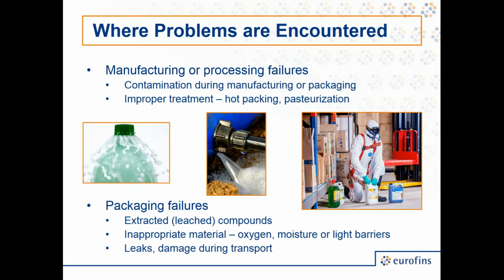So as we dig a little deeper into the contributing factors for where these problems come from, we like to go upstream because we all want to get to, obviously, root cause analysis and corrective action. So manufacturing and processing failures oftentimes are going to be during the manufacturing or within the packaging steps. And oftentimes it can be from improper treatment, like inadequate hot packing, pasteurization, maybe some type of contaminant that's present from a maintenance that went wrong, or a cleaning in place solution or cleaner that didn't get flushed out properly. And then your packaging failures, oftentimes you'll get extraction, leaching, migration of compounds, and that's really because the material maybe was not designed for an acidic product or a basic product, or you're using it at higher pressures or higher temperatures or lower temperatures than it was designed for.